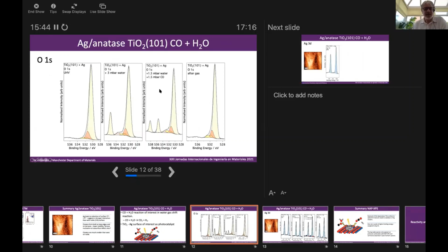So if we look at some oxygen 1s XPS spectra, the pale yellow peak here is the oxide substrate, the titanium dioxide substrate. Again, we've got this intrinsic feature and some hydroxides present on the surface and some other possibly carbon oxygen species as well. When we expose to water, we get exactly the same result as we saw on the clean titanium dioxide surface. We get the formation of hydroxides, maybe a little more carbon oxygen species, and we see molecular water on the surface. But we don't really see any significant changes in the oxygen 1s due to the presence of the silver.